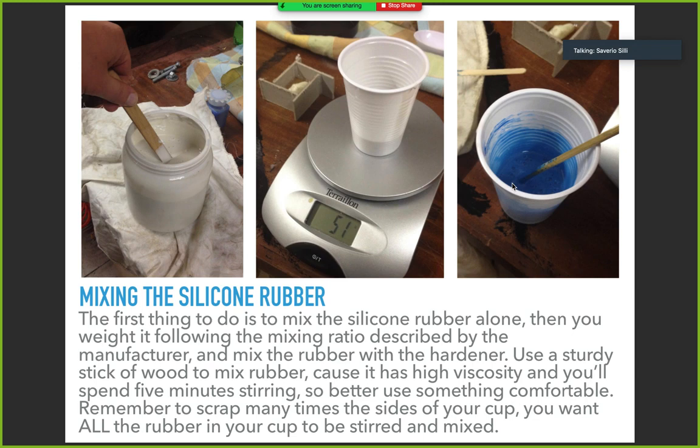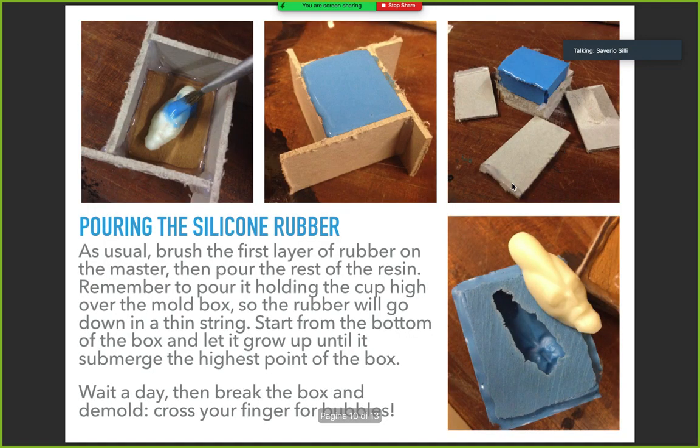In this case, the silicone rubber I was using was 100 parts of silicone rubber and 2 parts of the hardener, and then you mix the hardener. The rubber is pink or white, and the hardener is blue. This way, when you're stirring, you can tell that they are well mixed. If you are using OOMOO from Smooth-On, the good thing about OOMOO is that it comes in half and half. So 50% of one component, 50% of the other component. And you cannot make a mistake. Then again, I use the brush to brush the